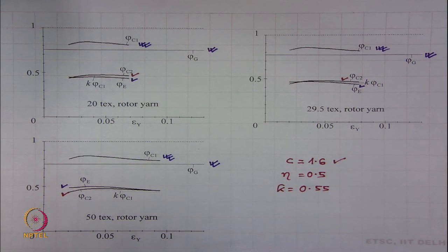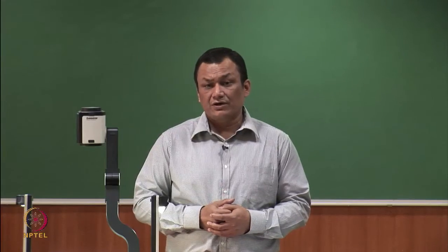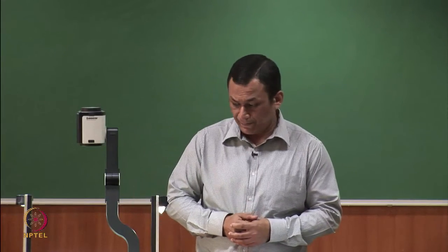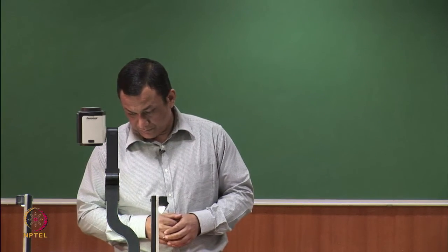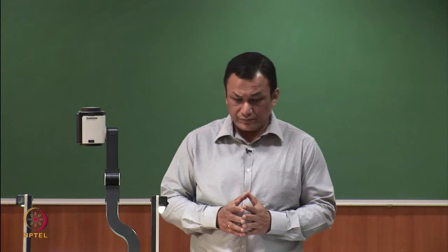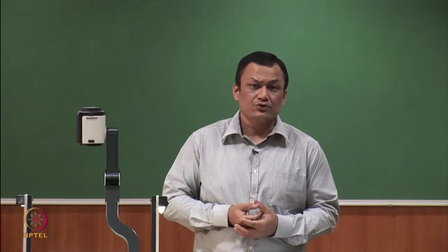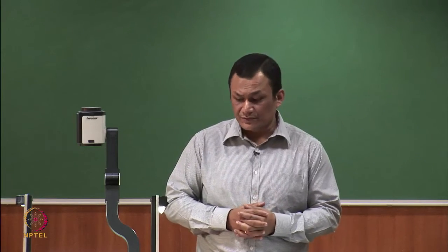However, the value of K was 0.55. This was probably associated with the more disordered character of fibers in rotor yarn, and it is also well known that rotor yarn deviates much more from the helical model.